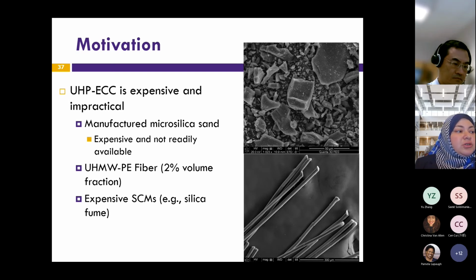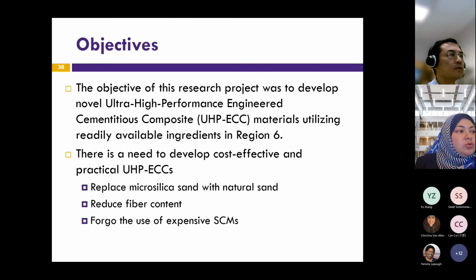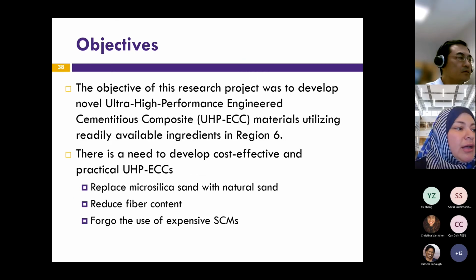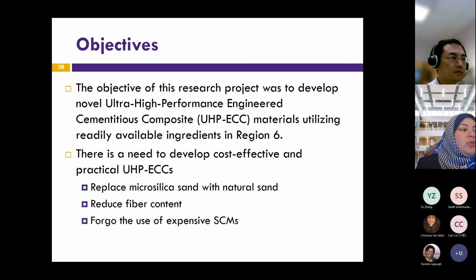But before we started our work, this was the best performance that we found from the literature. So we're looking at the use of ultra-high molecular weight polyethylene fibers at 2% volume fraction and very expensive SCMs like silica fumes. So again, to bring this back to practice and to actual implementation, we wanted to see if we can reduce the cost of ultra-high performance ECC and still design it successfully. So we wanted to again replace microsilica sand with natural sand, reduce the fiber content as much as possible, and get rid of the expensive SCMs like the silica fumes.